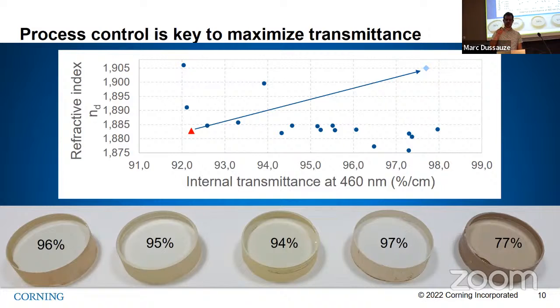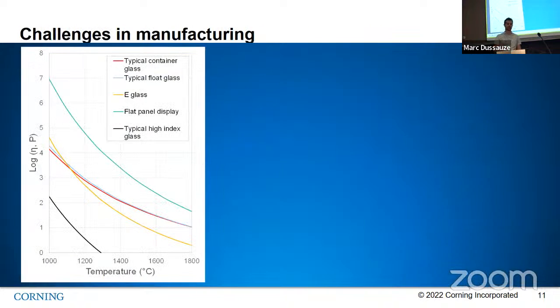So I showed you how we make the glass composition, how we melt it, but now we need to form it. And we have some challenges there also in manufacturing. So here I'm just showing the viscosity of some glasses. The first one on top, the green plot, is the typical viscosity curve of a glass used for flat panel display, so display glass. And in black, you see a typical high index glass. The first thing you can see is that the viscosity is much lower for those high index glasses. So we are in a very different regime. We are at only a few poise around the liquidus temperature. So you can imagine that forming this glass is going to be very different.